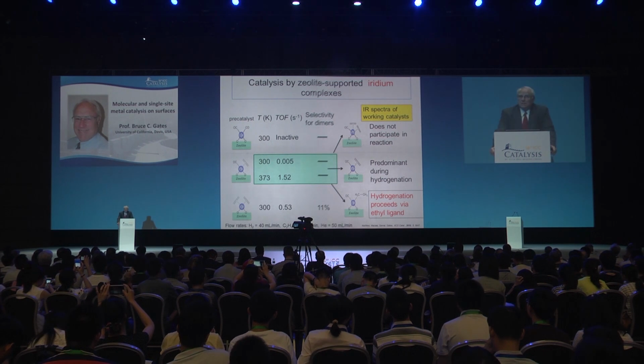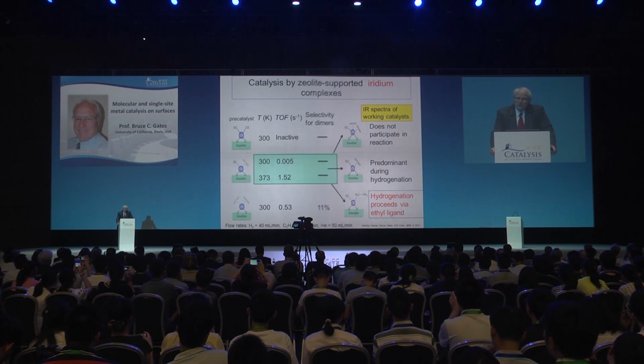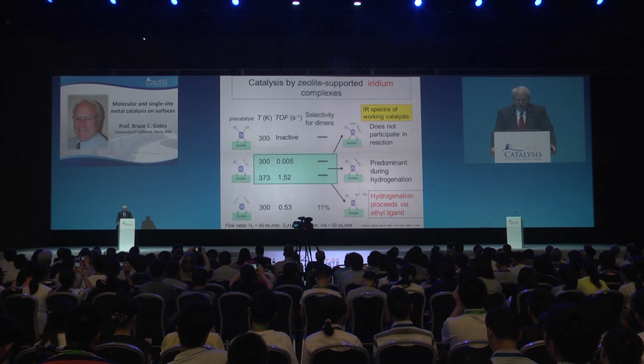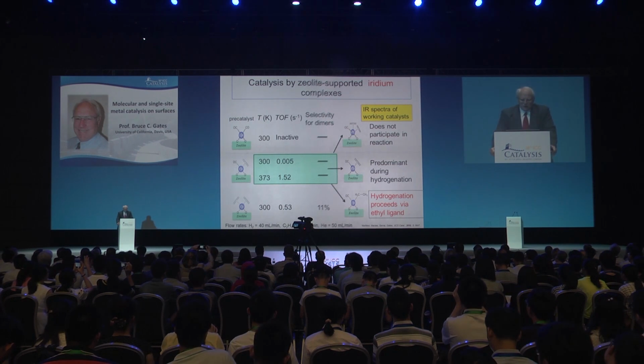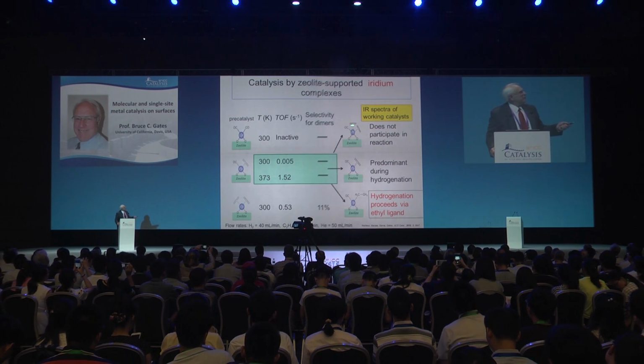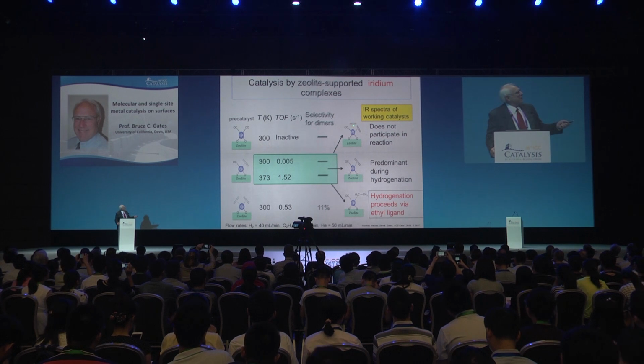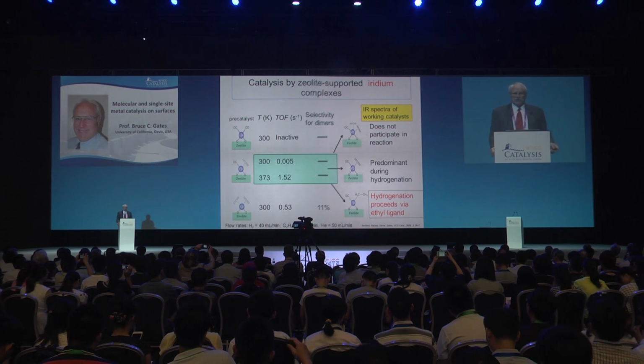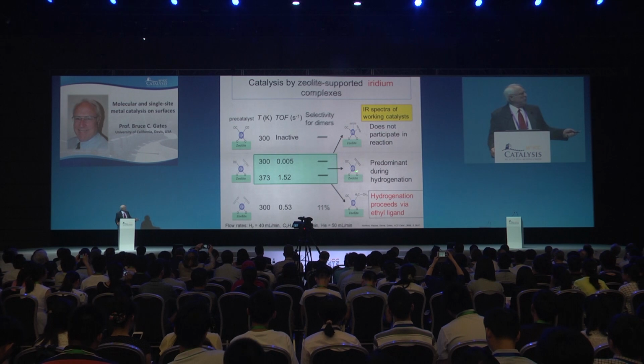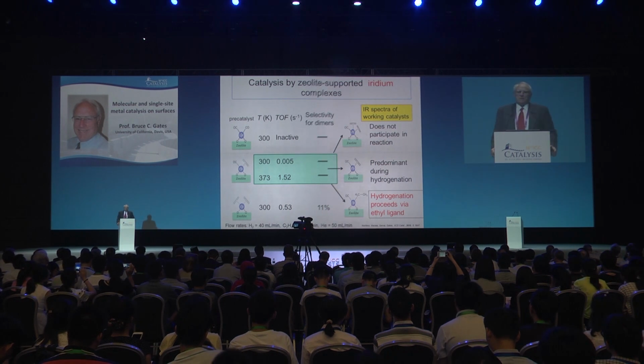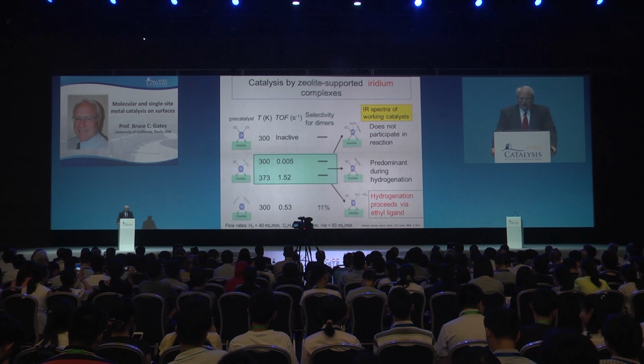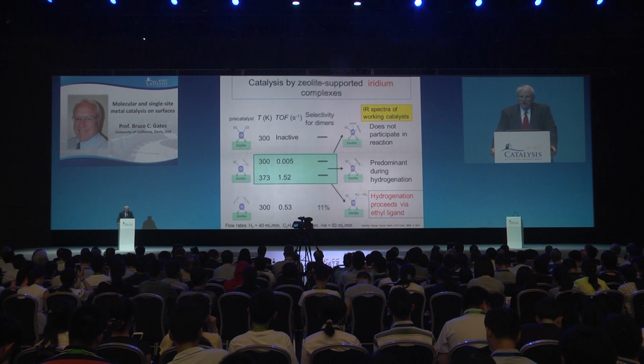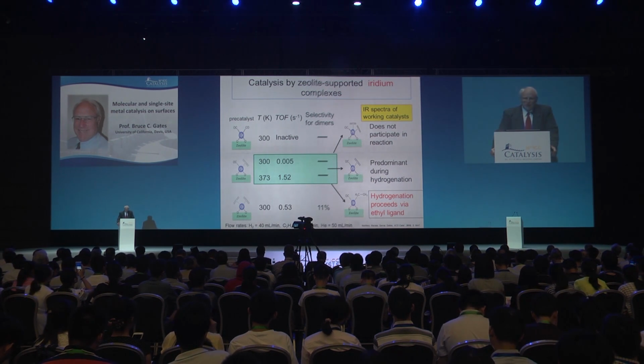What's going on? The infrared spectra of the working catalyst tell us. We're removing the kind of blocking ethylene ligand that exists at the lower temperature, and we make more of that species. That's a more reactive species, and we get higher activity when we depopulate the iridium of some of the ethylene. We also see ethyl as an intermediate.